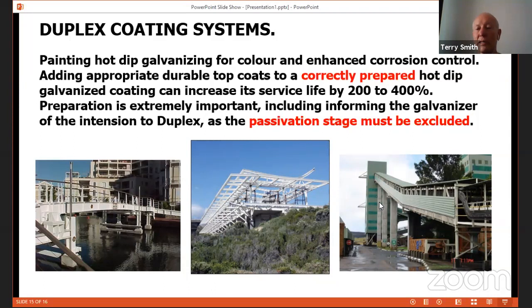This is Twistdraai Colliery, where the galvanizing was painted with a substantial paint system. This picture was taken after about 20-odd years, and there was nothing wrong with the coating whatsoever. Additional applications in mining, which is not happening in South Africa, but I just wanted to tell you a little bit about. Hot-dip galvanizing has been the coating of choice in deep level mining for more than 50 odd years.